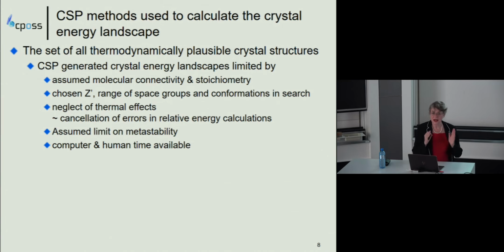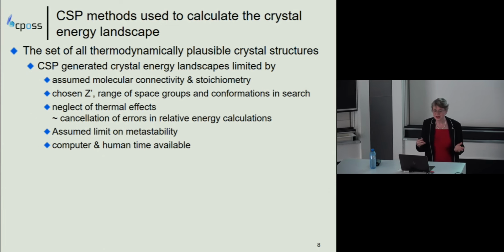It may be less obvious to you whether you're limiting your search to the conformational space that can be adopted by the molecule. We're neglecting thermal effects, and actually there are an awful lot of other approximations in what we're doing where we're relying on cancellation of errors in our relative energy calculations. We don't really know at what level of metastability we should cut off from being a plausible polymorph, and we're always limited by our computer and human time available for doing the work.